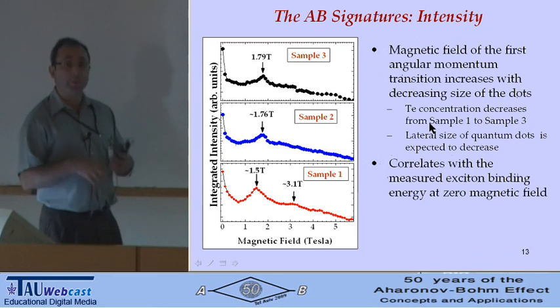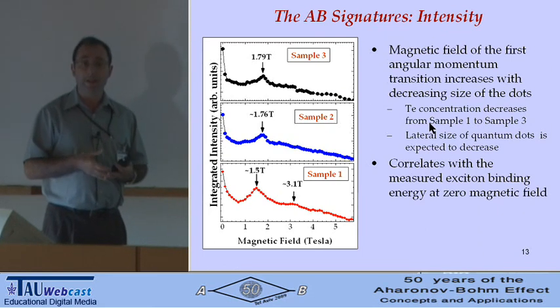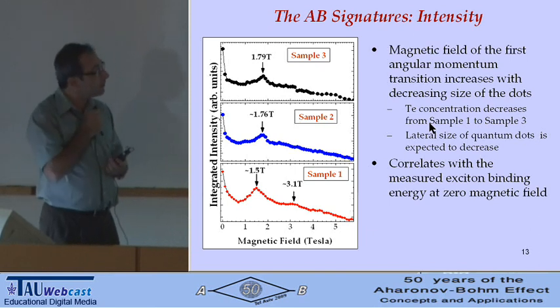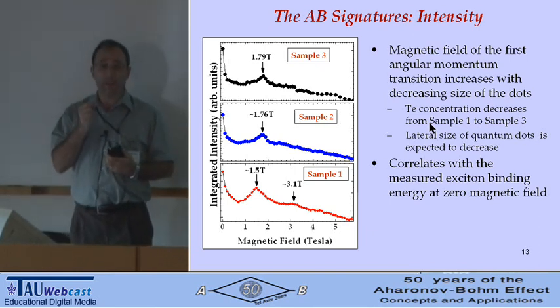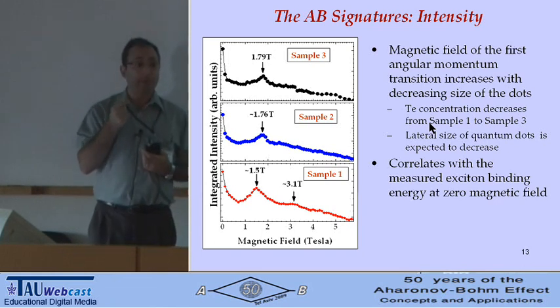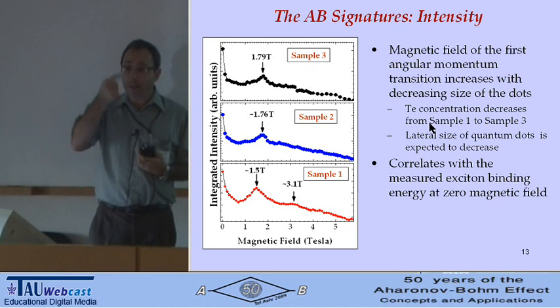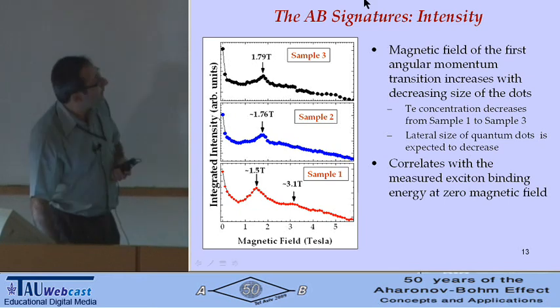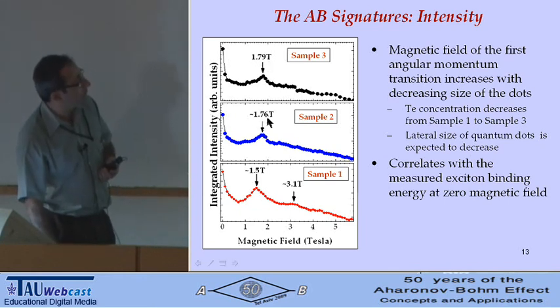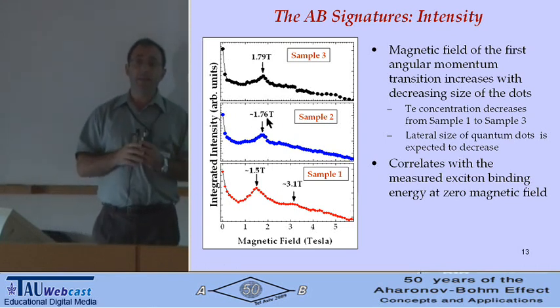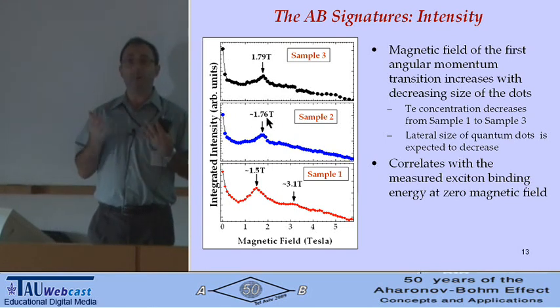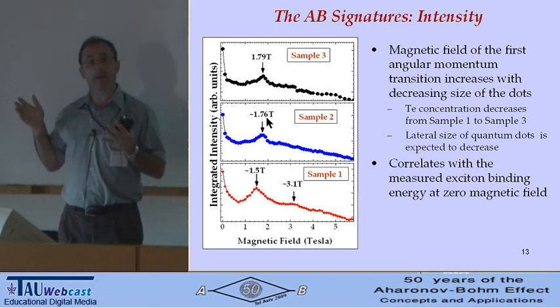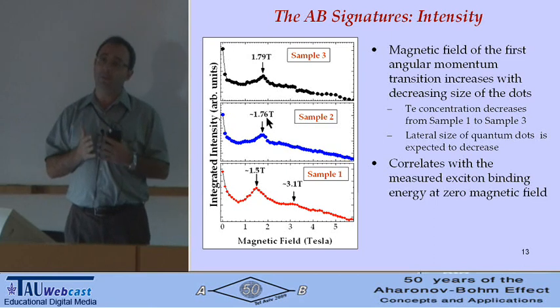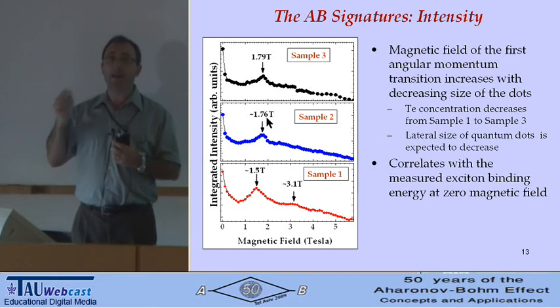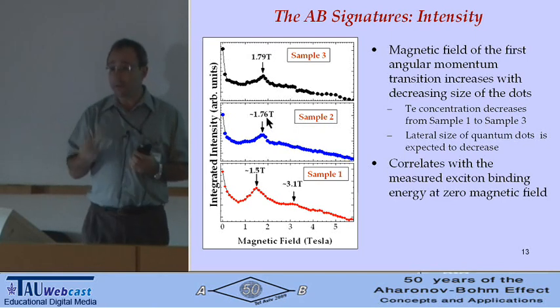We've done this for 3 samples with different sizes of quantum dots to show that it's really not a one-sample system. What is interesting, I'd like to point out, is that as a tool, these Aharonov-Bohm oscillations are very, very important, because the magnetic field transition goes as the inverse of the radius squared, and the magnetic field is to the first power. So if you take 1.79 Tesla versus 1.76 Tesla, it's very easy to resolve. That means if you recalculate, for instance, the orbit of the electron at 19.5 angstroms and 20.5 angstroms, it's very well resolved. So you cannot say this is approximately 20 angstrom. They're different. And this tool is very important, and we really saw that effect.